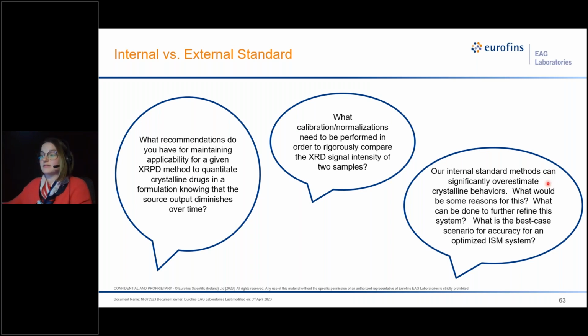And internal standard methods can overestimate or underestimate your crystalline materials. The reason for this is that the RIR in the program you're using for your standard doesn't have the actual correct RIR. So sometimes it's important to measure the RIR of your internal standard yourself. You can also make sure that your internal standard isn't reacting with your sample, and that the peaks for your internal standard aren't overlapping with the peaks of what you care about analyzing.